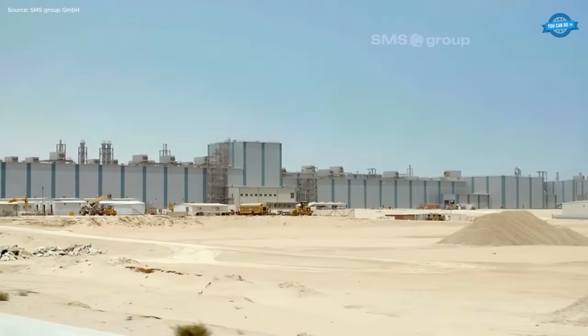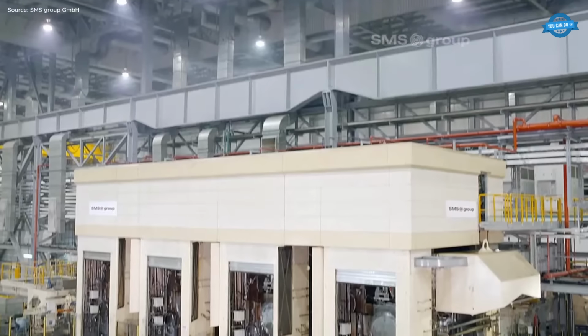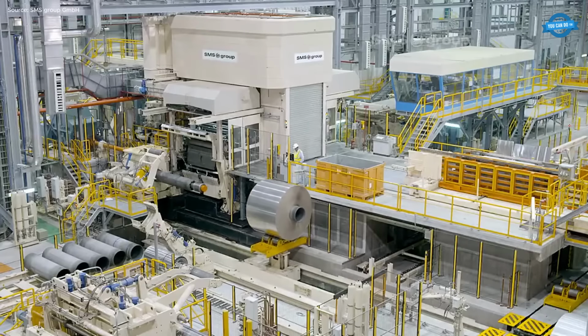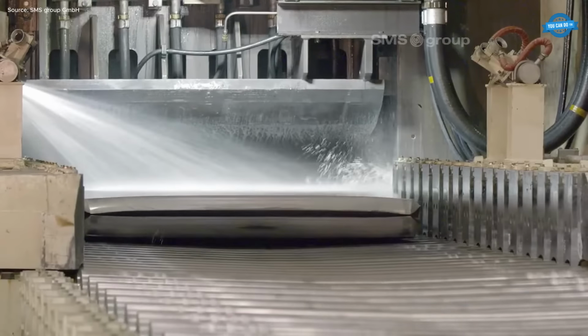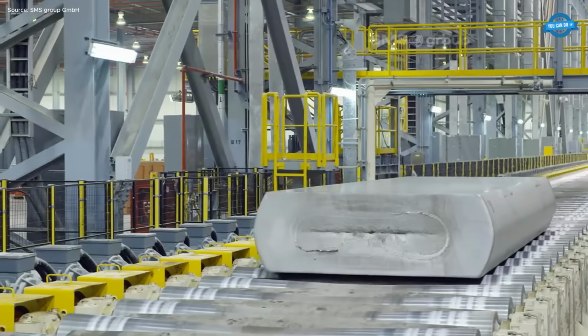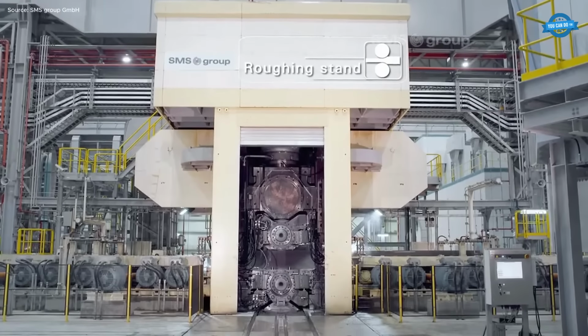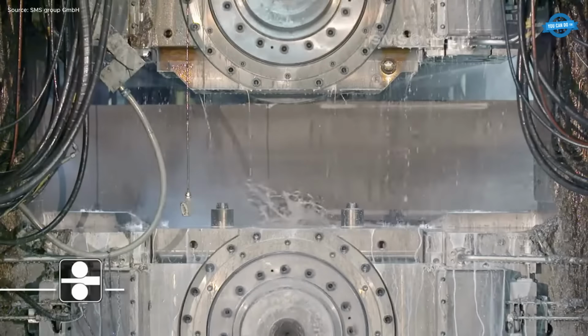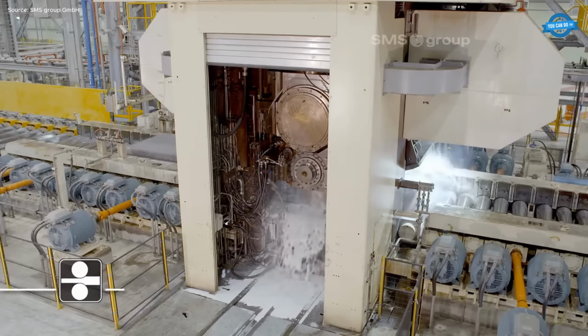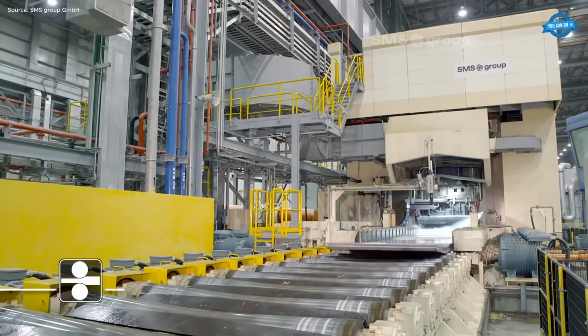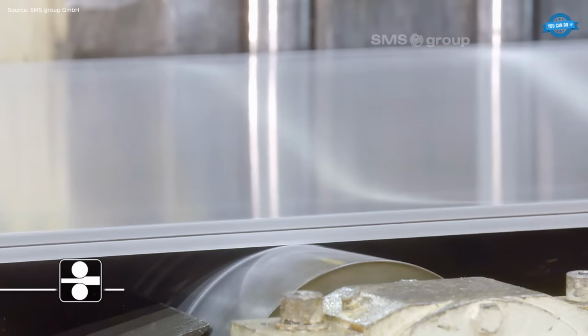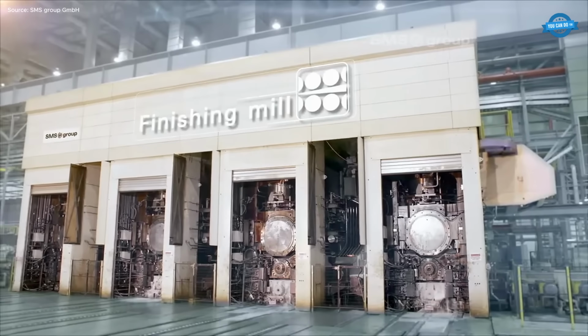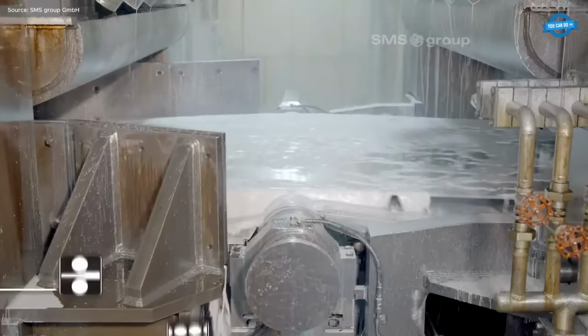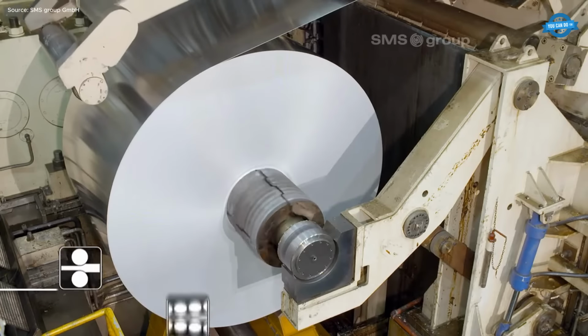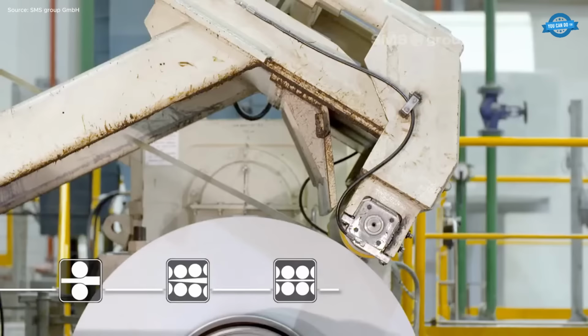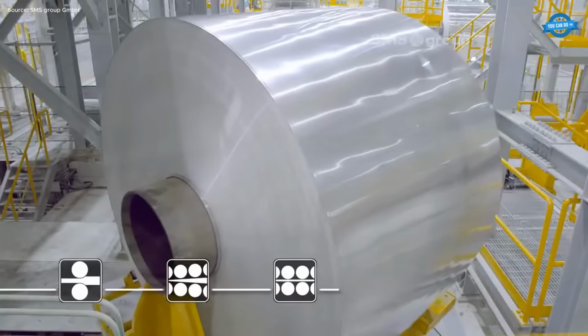In Ras Al Khair, Saudi Arabia, cutting-edge aluminium rolling meets large-scale industrial power. Designed by SMS Group, the Ma'aden Alcoa complex integrates advanced hot and cold rolling, heat treatment, and automation into one seamless operation, built to deliver ultra-thin gauges, perfect flatness, and consistent high-quality output. The line features a 1+4 hot rolling mill, beginning with 32.5-ton, 635 mm thick ingots, reduced in a 4-high roughing stand, followed by 4 finishing stands to reach 2 to 7 mm strip thickness.